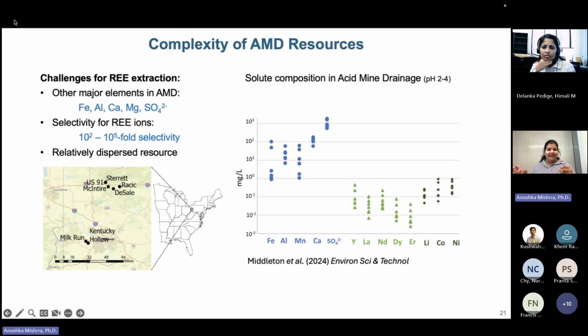And at the same time, when you compare the critical metals, they're present in micrograms per liter. So we're looking at maybe 500 or 1,000 or even like 50 micrograms per liter of these REEs. So this big difference in the different types of metals present in this acid mine drainage fluid actually makes it difficult for extraction. And also, partly the reason why rare earth elements are called rare, not because they're actually less, but the extraction process is really tough around rare earth elements, because we have other co-associated metals which are present at high concentration.